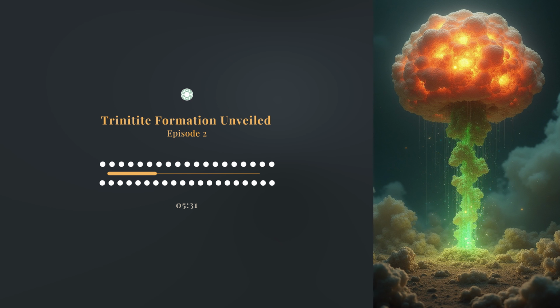And everything else, the feldspars, the mica? All melted, completely. So you end up with this glassy matrix, this sort of background material, with bits of partially melted quartz kind of floating in it. That's a good way to put it. And the glass itself, if you look under a microscope, is incredibly complex. It's really heterogeneous, meaning it varies a lot over tiny distances, like tens or hundreds of micrometers. So not uniform at all.